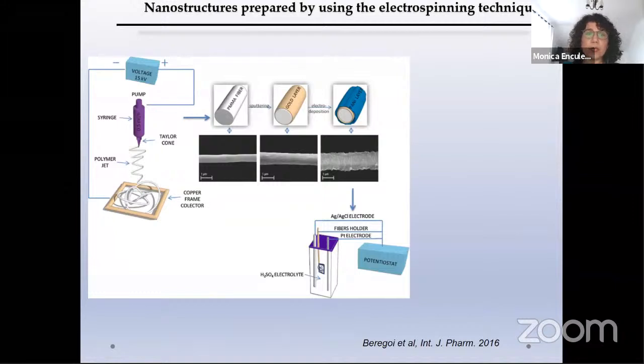So in this slide, I will shortly present the way in which we can cover our fibers with a conducting polymer, for instance, to obtain functionalization. So it is, of course, the deposition of the fibers. This is a very nice fact about the electrospinning, that we can change the substrates. So we can deposit this type of fibers on any substrate that we want. It can be metallic, it can be flexible, like paper or like plastic, because we can collect those fibers on a frame. If we have a metallic frame, then we can collect those fibers on a frame and we can transfer them on any substrate that we want to use. So we have the fiber, which is further sputtered with a metallic layer.